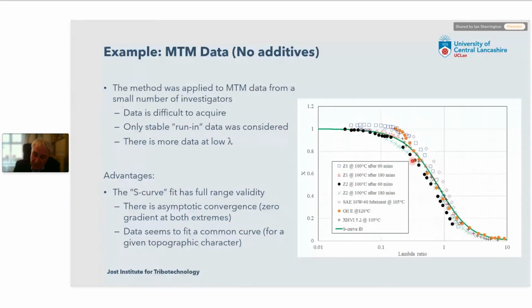We were specifically interested in trying to get hold of run-in data, so that this is data that is stable. It doesn't change anymore with the operation of the machine. So it's quite easy to get data off this curve, but not for data that's run in. We also see that we've got more data at low lambda, and so this fit curve that we've created, the green line, is somewhat distorted because it fits better where there's more data, and it doesn't fit quite so well where there's less data. So we recognize that.